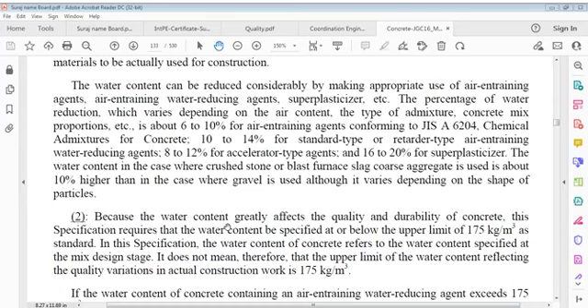For chemical admixtures for concrete: 10 to 14% for standard type or retarder-type air entraining water reducing agents, 8 to 12% for accelerator type agents, and 16 to 20% for superplasticizer. Water content in cases where crushed stone or blast furnace slag aggregates are used is about 10% higher than in cases where gravel is used, although it varies depending on shape of particles.